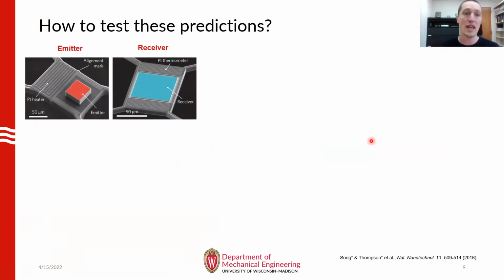The approach relied on fabricating the two microcalorimeters that you see in these electron micrographs. The first device is called the emitter, and the device on the right is called the receiver. Each of these is comprised of silicon, and it's essentially a suspended structure supported by four long and thin support beams, which help to thermally isolate the structures. Each device also has an integrated thin film platinum line, which can be used to either heat up the structure or measure its temperature rise. Also, each of these devices has a planar pad, here false colored in red and blue respectively, which can be made to be extremely flat and extremely clean.